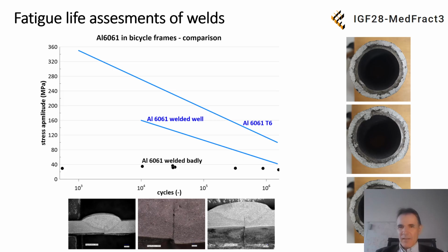The middle one is the S-N curve for weld joints, when the weld joint is done appropriately and correctly. Down here, the black points are the real results from testing of these two tubes, recalculated as a nominal stress. These points are rather lower and lead to a very low allowed maximum stress amplitude for this insufficient weld. This is a very surprising fact, but this is the reality from the producers.